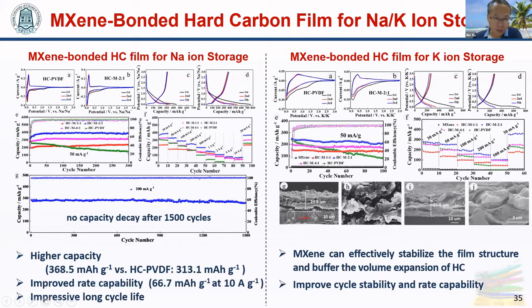Being used as anodes for sodium and potassium ion batteries, MXene bonded hard carbon electrodes show much better performance than the conventional PVDF bonded electrode. We can see for sodium ion storage, this is a PVDF bonded electrode. This is for the MXene bonded electrode. It has higher capacities and very stable cycle performance. During 1,500 cycles, no capacity decay was observed.